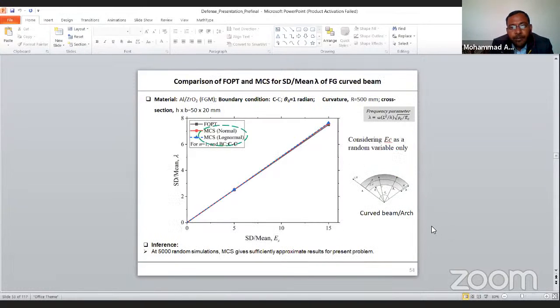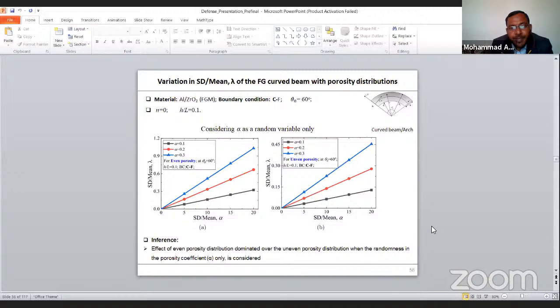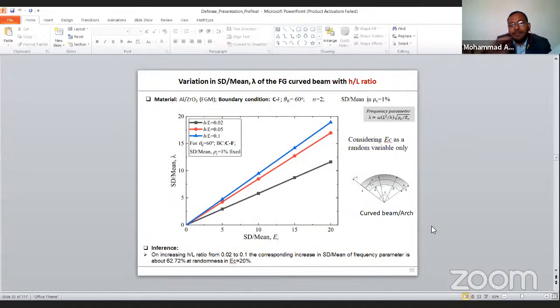And one more thing here. Here we consider the randomness in the density only. By fixing the randomness in the density at 1%, we increase the randomness in the Young's modulus of the ceramic. By increasing the randomness in the ceramic, the randomness in the frequency response is also increasing. For different H by L ratios, for H by L equal to 0.1 it is maximum, and it is minimum for 0.02.